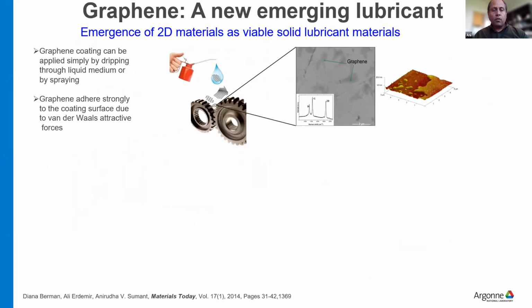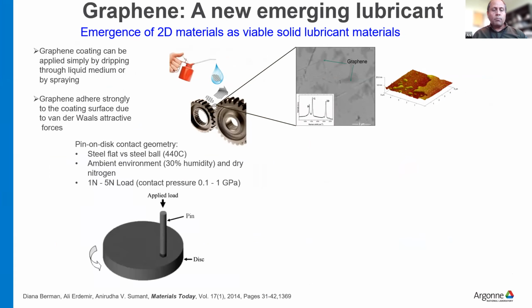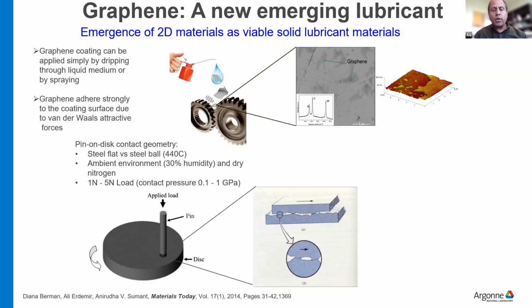And then we started knowing more about how graphene works as a lubricant. If you see the graphene here sprinkled on the stainless steel surface, it's very discontinuous in layer, as you can see in the SEM image. The way we test it, you sprinkle it on the surface, then there is a pin, which is a steel ball, and a steel plate, and you apply some pressure, and the steel plate is revolving in one direction. The tangential force on that pin gives you the friction coefficient by using Amonton's law, using a multi-asperity contact where friction force is directly proportional to load with a constant mu, which is the friction coefficient.